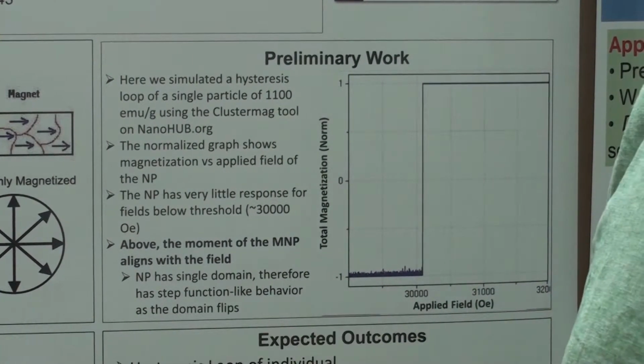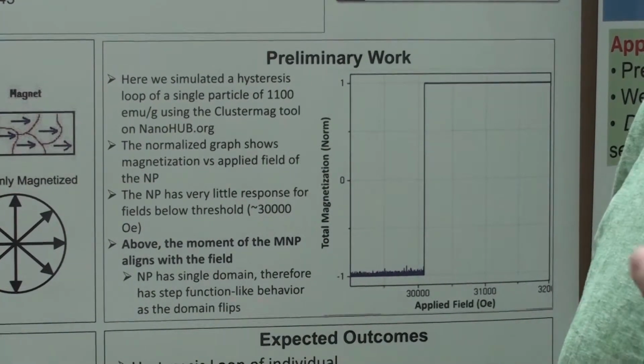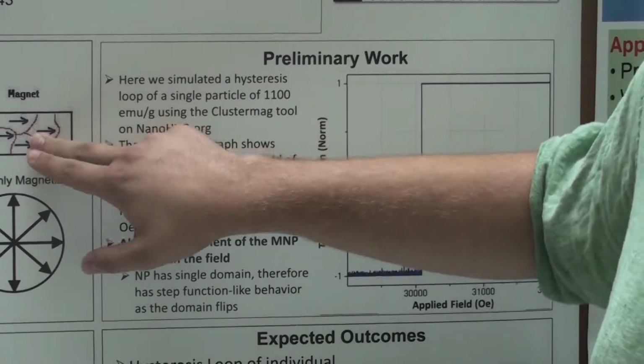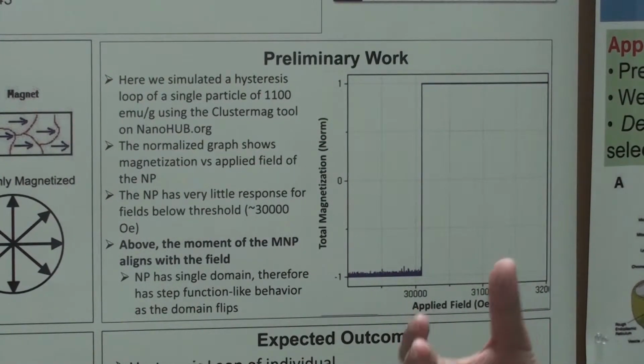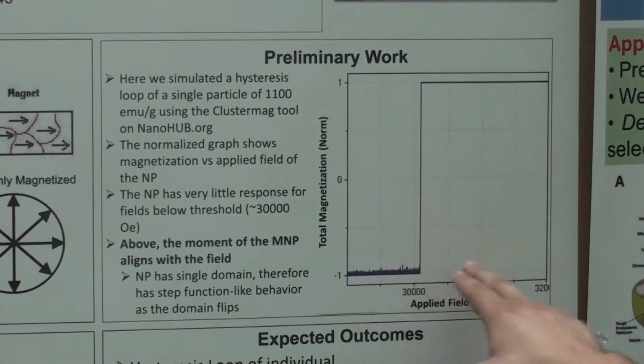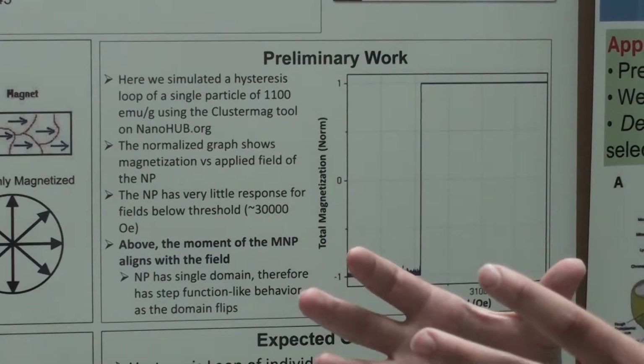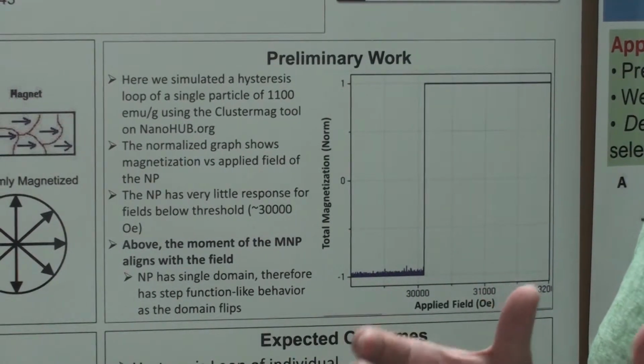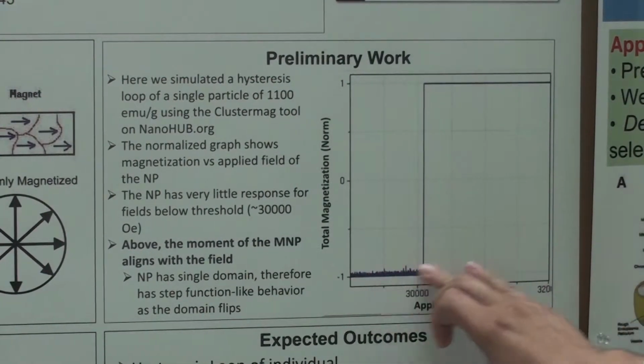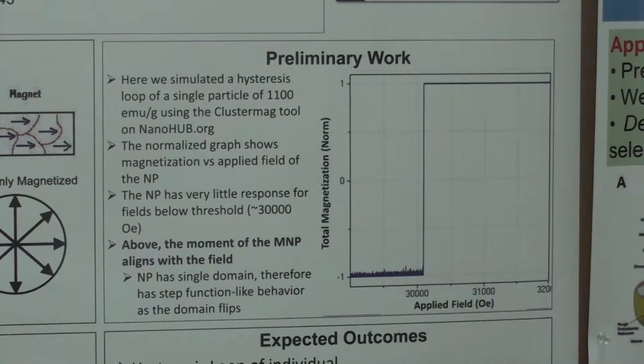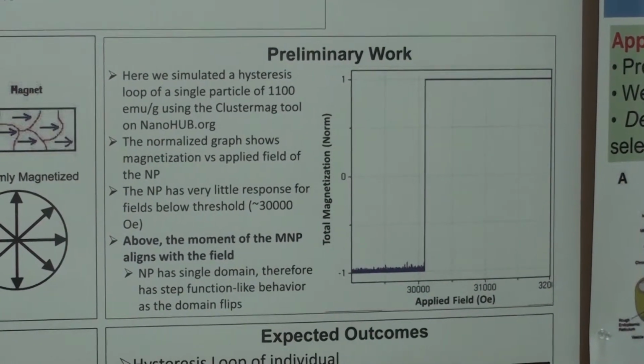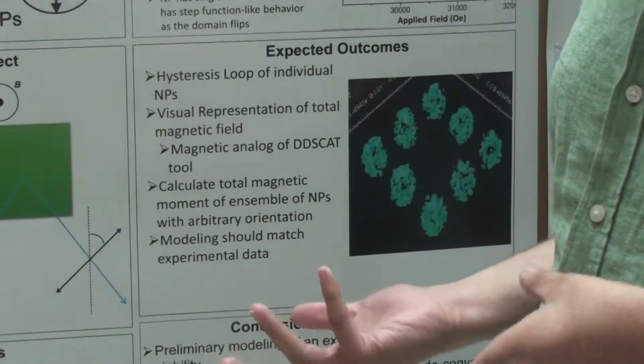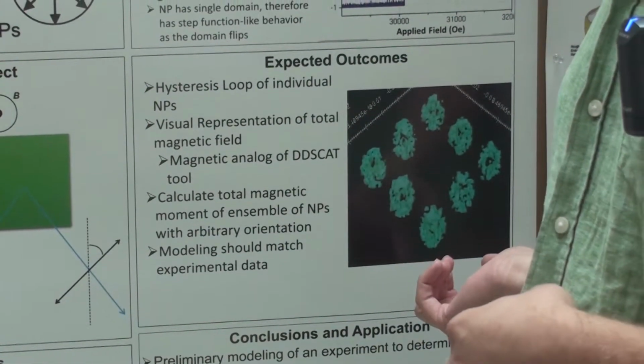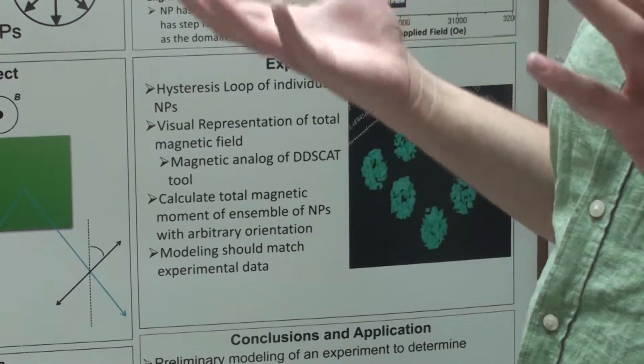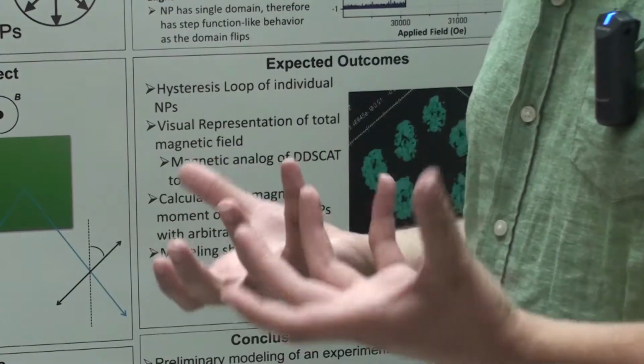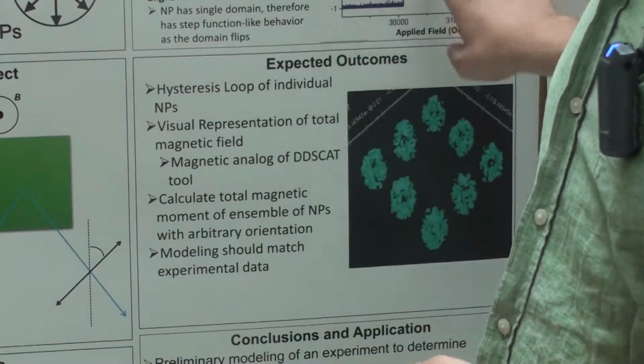which means that it doesn't remember any of the magnetization you applied to it before, which a lot of bulk iron does. Okay. Now I'm interested in observing this effect and seeing whether pushing clusters of iron oxide nanoparticles together changes this applied field, or changes the threshold. And the final result should be something like a magnetic analog of DDSCAT, which should give you the total magnetic moment and the hysteresis loop.